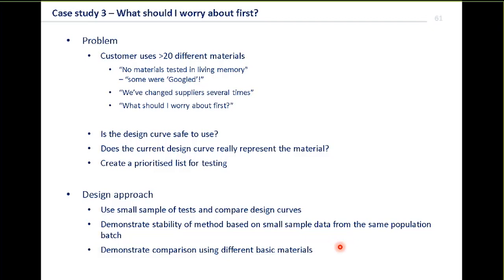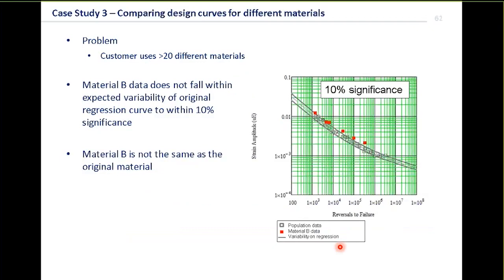Now, if we were trying to characterize a material from the ground up, as we saw earlier, you need at least 15 to get the regression curve, typically 25 if you want to get a design curve from that. But here we're using small numbers of tests just to start to see how far out we are with the data that they're using. So here we've got a comparison of new material B with the original design curve. So if we've got the design curve, we can start to see that. And here we've done a 10% significance on these bands, and we can see that material B, first of all, is not the same as material A.